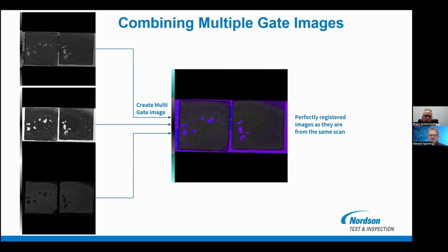So we're now using AIML to take the different layers. In this case, I'm showing three different layers. The AIML takes those three layers and combines them all into one image. And then we're using machine learning to teach it what the defects are. There might be features in these samples where a brighter pixel is the same brightness as a defect, but using AIML we can teach it what the defects are. Then through a learning process, it'll develop a model based on that, and we can use that model to do the analysis of the wafer.